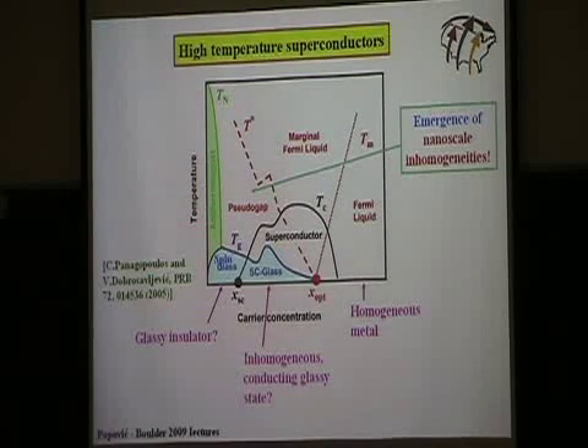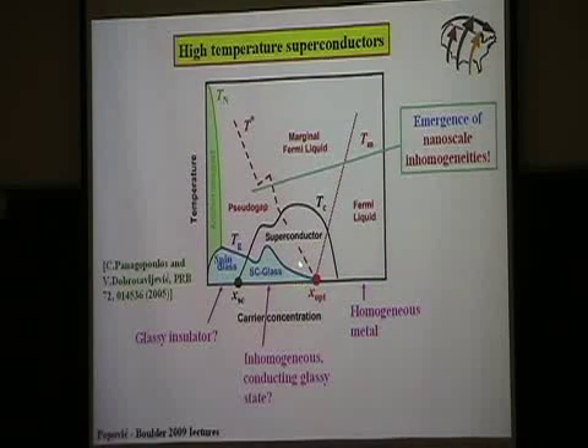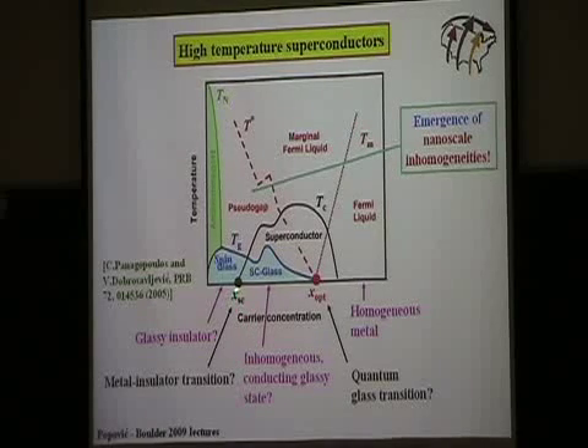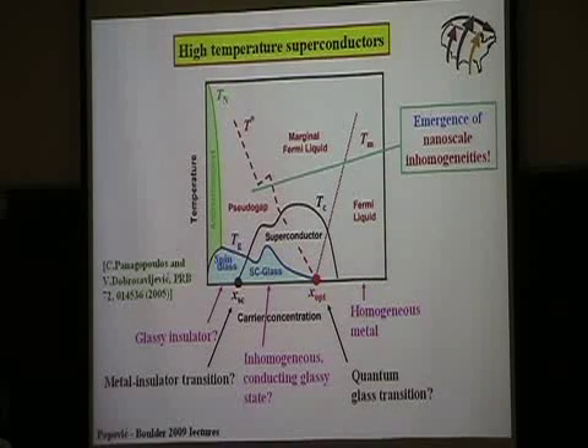So in this paper, they looked at the available experimental data, and it seems that perhaps these charge inhomogeneities vanish only also here at optimal doping. Now, if this scenario is true, this would mean that the insulating phase here, which may be a charged glass also, is separated from this nice metallic phase at very high doping by some inhomogeneous conducting glassy state. So you would have two transitions, right, from an insulator to a conducting state, and also a transition from a glassy phase to a nice metal. So why is this interesting?